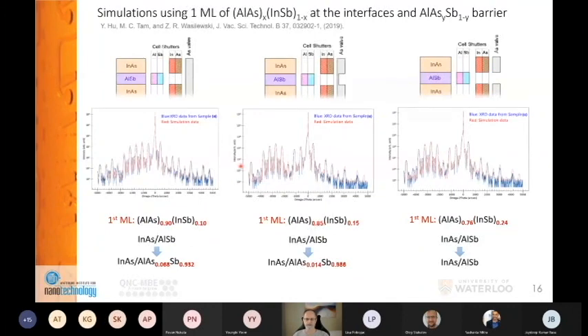diffractometer to run the omega 2 theta scans and then performed the dynamic simulation fitting to simulate strain in the layers, which would be induced by the presence of arsenic at the interface and in the aluminum antimonide itself. And what we found, I would just focus only on the fully open and fully closed valve during aluminum antimonide growth for this brief discussion. What we found is that indeed,